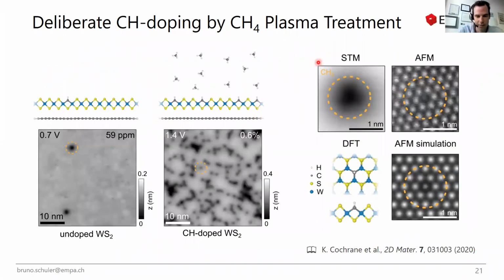And then similarly to introducing these transition metals by bottom-up means, what we did is expose this tungsten disulfide layer to a methane plasma to introduce carbon dopants. And as you can see quite easily here, there is quite a drastic change if you do this. You see a lot of these negatively charged defects, all these dark looking things, so that you can change the concentration from about tens of ppm, which you usually have due to some impurities, to something which is more in the range of a 1% defect concentration.